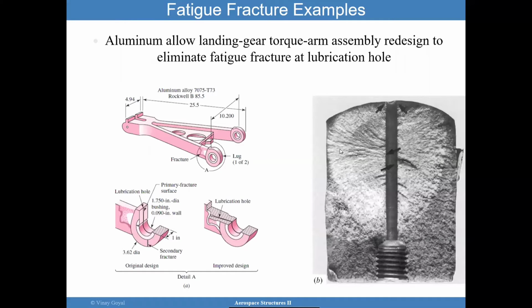Here you have an aluminum alloy landing gear torque arm assembly, which required a redesign to eliminate fatigue fracture at the lubrication hole. And so again, fatigue fracture can occur in these types of stress concentrations. And in this case, I ask you to feel free to pause the video and see if you can see signs of the crack initiation and the growth and what could have been the growth failure.